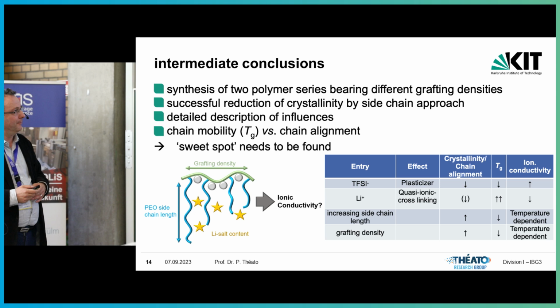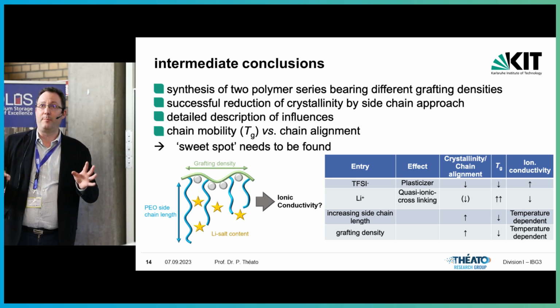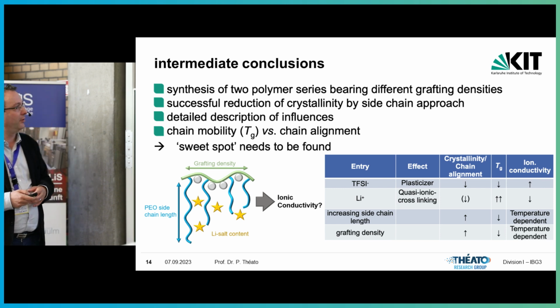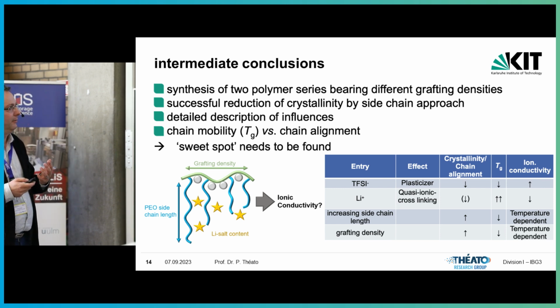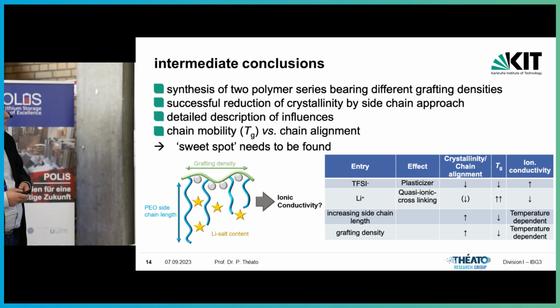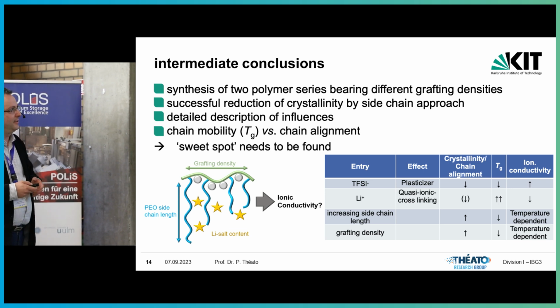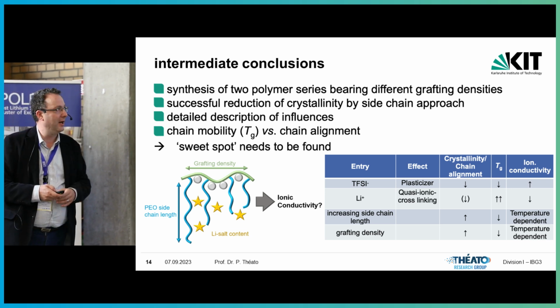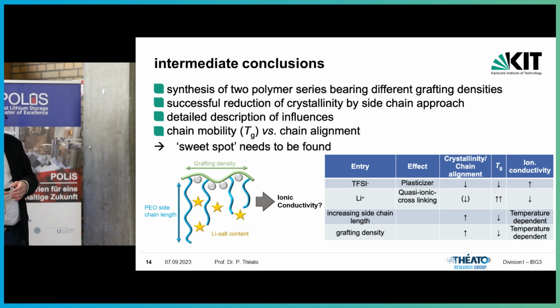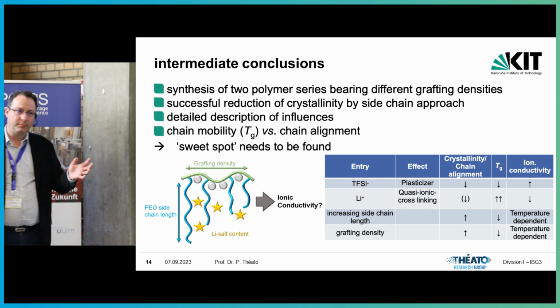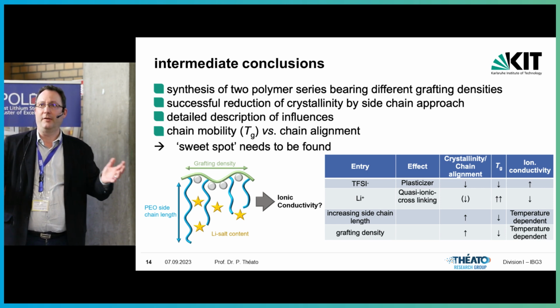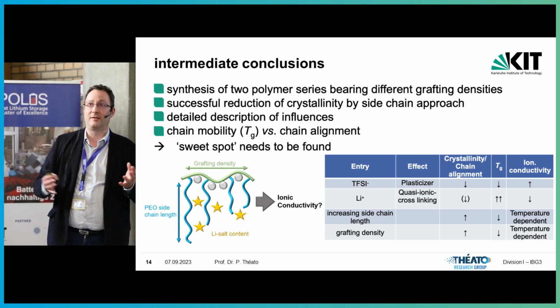Intermediate conclusions. There is no one system that suits all. It really depends on what you would like to have, because different factors are not necessarily in line with each other. So we have the side chain lengths, the density, and of course the quasi-cross-linking density, and we excluded for now, of course, the plasticizing effect of the counter anion. This is very nice. So we learned something, but these systems are practically useless because they're not mechanically stable.